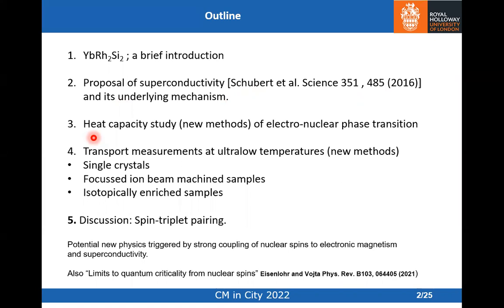And there I'll show data of what we'll refer to as an electro-nuclear phase transition, then spend some time talking about the transport measurements at ultra-low temperatures, which also involve new methods for working in this extreme temperature regime. And so we have data on single crystals, samples, effectively wires of YRS machined by focused ion beam techniques. And we also have results on isotopically enriched samples. Have some discussion about the possibility of spin triplet pairing.